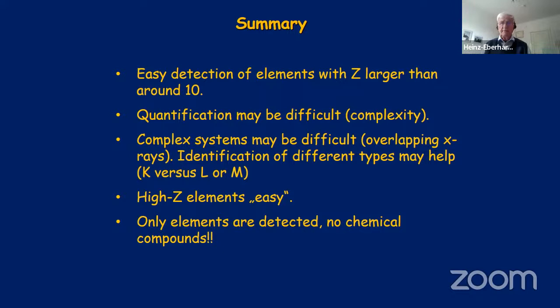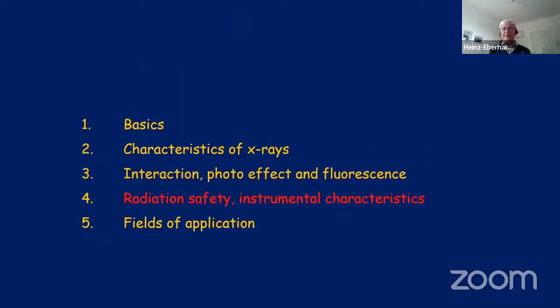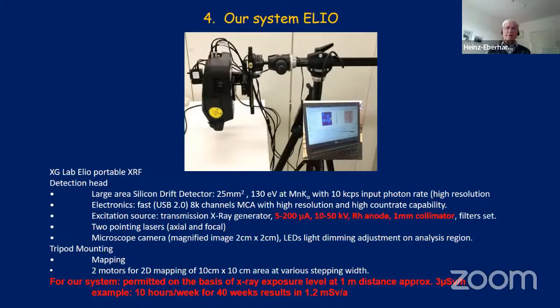You are much easier off if you have only high Z elements, because then the separation in energy is easy. But you have to be aware that you only detect elements just by the signature from the energy, not the chemical compound. If you want to determine what kind of chemical compound you have, you have to go to different techniques. Radiation safety for handheld X-ray fluorescence systems is not so much of a problem, because you can only go very close to the object you want to analyze, typically about 1 centimeter. If it is just at a wall or a rock, for example, then there is no problem. In open arrangements of the setup, you have to be at least about 1 meter apart from the system, then you are on the safe side.